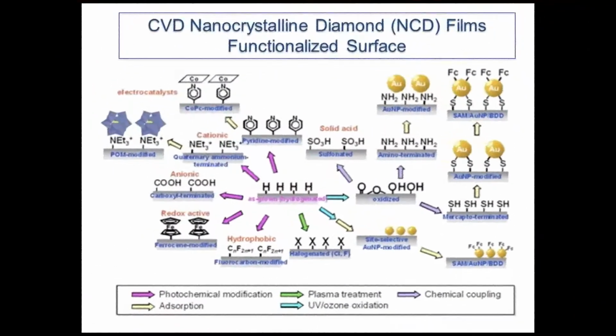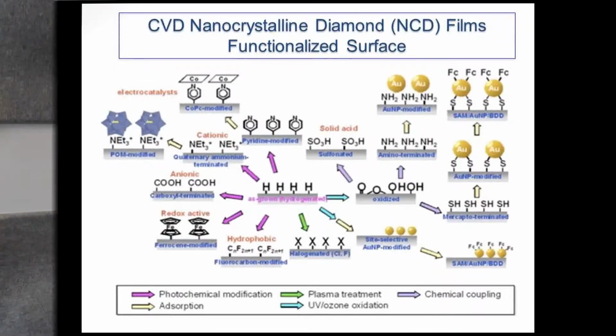The main reason why we use diamond in the MOLESOL project is that we can make a very thin layer of transparent diamond on any type of substrate. But most important is we can make it electrically conductive, and being diamond, it is a carbon surface which can then be functionalized, forming very stable bonds with all kinds of dyes.